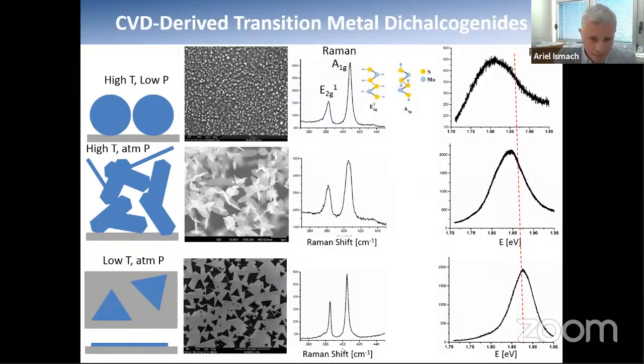Now, one of our methodologies to try and improve the growth of these materials, and also to study the mechanism, was taken from many other fields, for example, 3D crystal growth or even colloidal growth, and is what we call the seeded growth approach, where you start the nucleation from well-defined seeds. By doing that, in many fields, you can, in principle, control the crystal orientation, the shape, the size. In colloidal synthesis, you can control the size distribution, for example, the chemical composition, and so on. This is the basis, for example, of our silicon technology as we know it today.